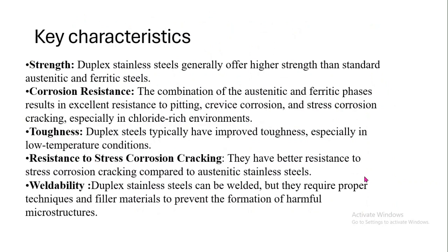Normally, duplex stainless steel has higher strength than other stainless steel such as austenitic and ferritic stainless steel. It has more strength, and in case of corrosion resistance, it has very excellent corrosion resistance. Specifically, it is more resistant to pitting corrosion, crevice corrosion, and stress corrosion cracking, because it has a combination of austenitic and ferritic phase. Due to that, it is more resistant to pitting, crevice corrosion, and stress corrosion cracking, even if it is used in a chloride rich environment.